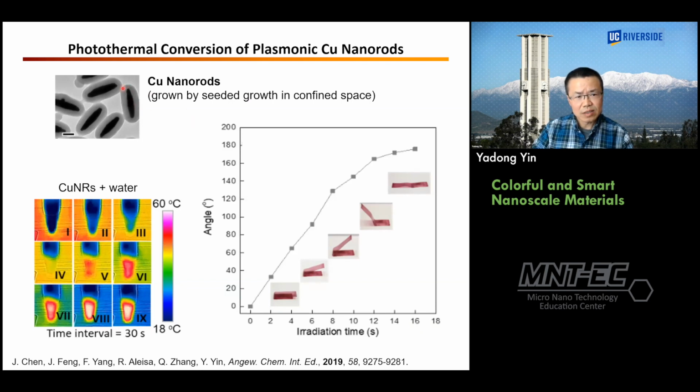That's why, as you can see here, this structure is made with a coating, a cross-linked polymer coating, and that makes the copper very stable. It isolates the chemical environment, so you don't have much oxidation going on. For most applications we don't have to worry about stability once you have the protection. Yeah.